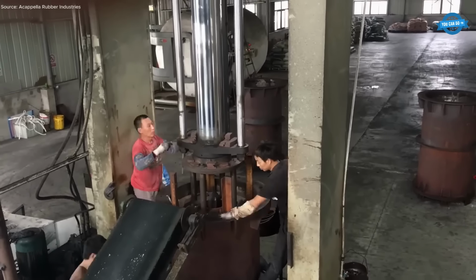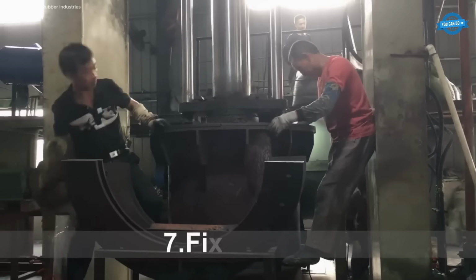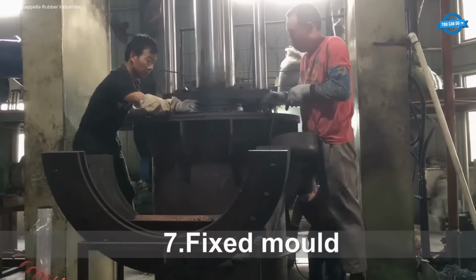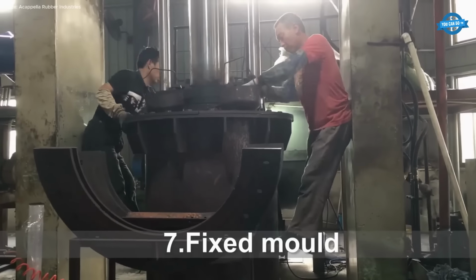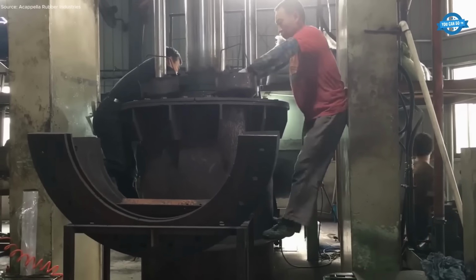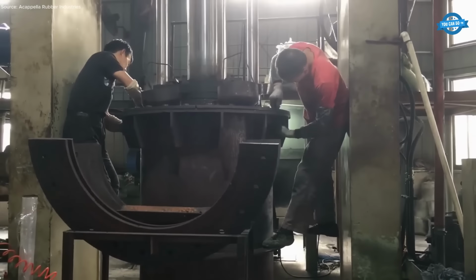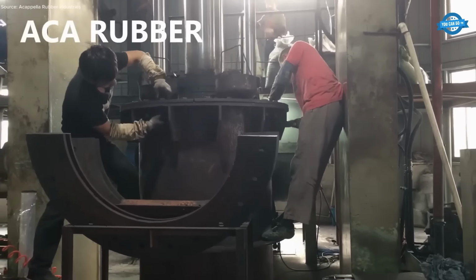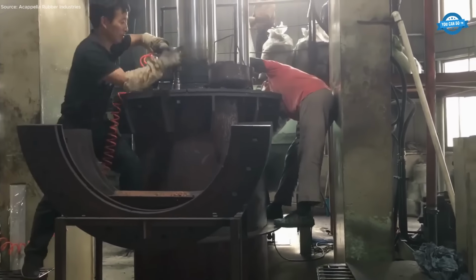Next, the cleaned EPDM crumbs, including colorful flecks for aesthetic appeal, are loaded into a mixer. For every 8 kilograms of crumbs, 1 kilogram of PU binder is added to ensure proper binding and structural integrity. The mixture is blended for 8 minutes to achieve uniform consistency, a crucial step to ensure the colored flecks are evenly distributed and the binder coats each crumb thoroughly. This uniform mixing enhances the mat's strength and visual appeal, preparing it for molding.